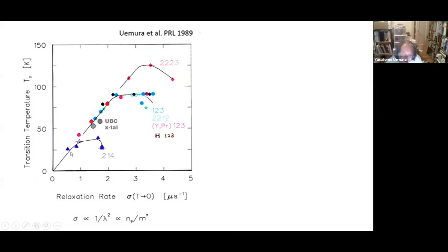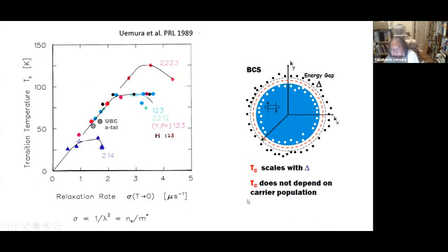And especially in the underdoped region with increasing doping, we found that Tc follows a nearly linear relationship with the superfluid density. And that was one of the first definite indications that the condensation is not BCS-like, because if you have a BCS superconductor, the Tc is determined by the energy gap delta, and the superfluid density is essentially all the carriers in the Fermi sphere, as long as this Fermi sphere is protected by an energy gap, even a small gap.